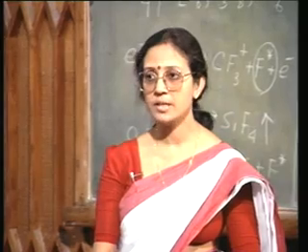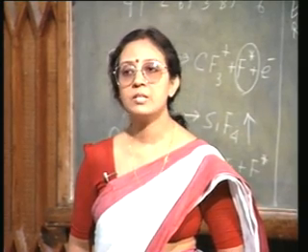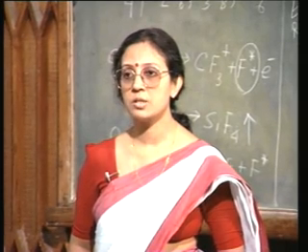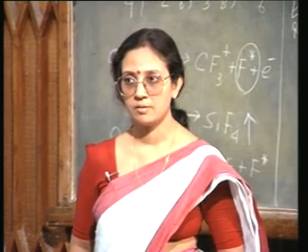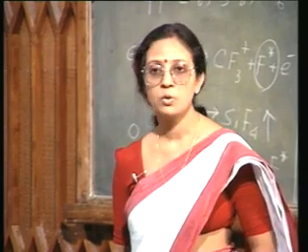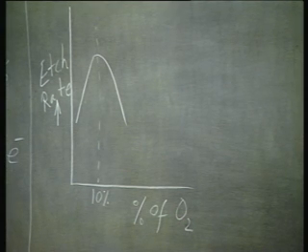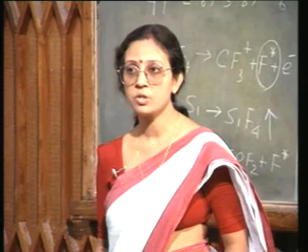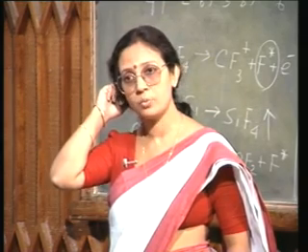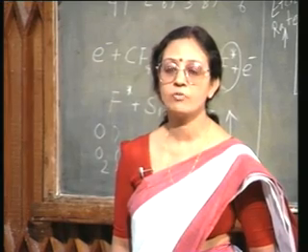Okay. So, from this you see, we have actually pointed out a quite important fact, that is the selectivity of fluorine based etching. The most common two things you need to distinguish between are silicon and silicon dioxide, right. And I have already told you that the etch rate of silicon dioxide is going to be much smaller than that of silicon when you use fluorine. That is why here you see the etch rate is decreasing. If you have actual silicon dioxide, the etch rate is going to be much, much smaller, right. So, you have good selectivity if you use fluorine, because the etching is taking place by the chemical reaction, the reaction of active fluorine species with silicon, and its selectivity over silicon dioxide is quite good. In fact, you can realize a selectivity of 40:1.